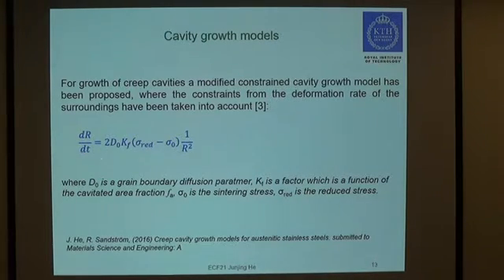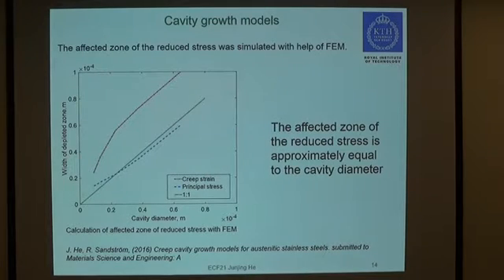The final equation of the cavity growth model is related to the grain boundary diffusion parameter. Kf here is a factor which is a function of the cavitated area fraction. Sigma 0 here is the sintering stress, and sigma red here is the reduced stress. Mainly in the modified constraint cavity growth model, we have calculated the reduced stress with the help of FEM. The affected region of the reduced stress is approximately equal to the cavity diameter.